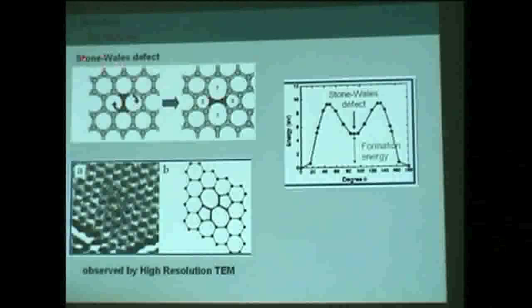And this defect is called a Stone-Wales defect. It was predicted a long time ago, because it's quite easy to make. The energy needed to turn this C-C bond is not very high. You need to go from this state to this state, and you see that the activation energy to go from this very stable state to this defective state is not so high.